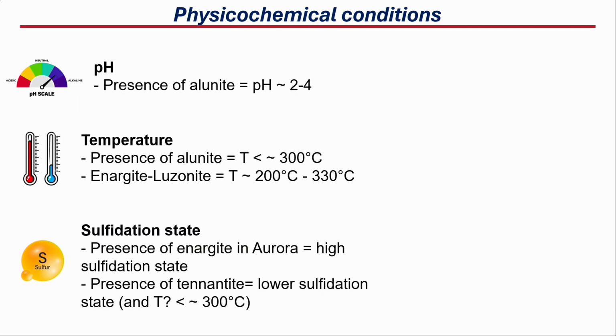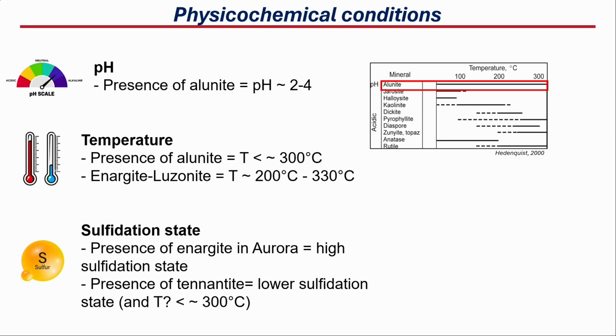So I tried to talk a little bit about the processes, and now I will mention some of the physicochemical conditions. So regarding pH, we have a lot of alunite in the system. Much of the alunite is co-precipitating with this pyrite. And since we know alunite is stable between 2 and 4 of pH, we need very acidic conditions to form these pyrite types. So in this image, I just had an image from Hedenquist 2000, where we can see that alunite gives us that range of around 3 of pH, but also this is stable at less than 300 Celsius of temperature.